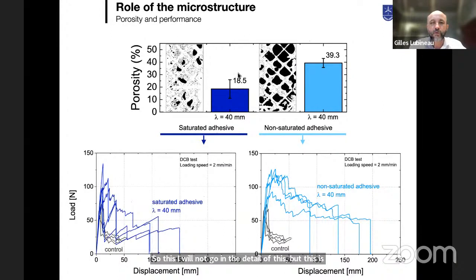I will not go into the detail on this, but this is very related to the level of porosity that you are able to control between the thermoplastic and the thermoset. If you don't introduce enough porosity, what you will see is that the improvement is very limited compared to the initial configuration. That means if you go to the dark blue curve, that is the delamination curve that you get in case of delamination without porosities, but you get a relatively limited improvement compared to the control sample in black here. But as soon as you control the morphology of your porosity, you see that the improvement is huge compared to the control sample. And why? Mainly because if you introduce porosities, you give a lot of freedom to the thermoplastic to deform and to stretch during the delamination. And this is what is important.